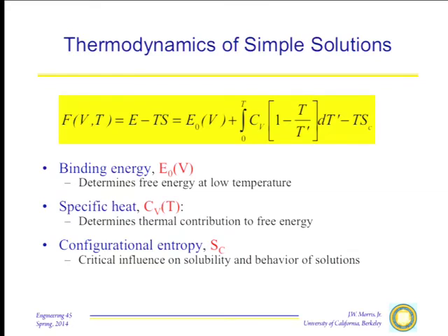It has, for example, as I'll show you in just a few minutes, the consequence that there is absolutely no such thing in the whole wide world as insolubility. You may have been taught in your chemistry course at one point or another that this oil is insoluble in water. Not true. Everything is at least a little bit soluble in everything else. And the reason is because of this configurational entropy, which always drives two components to mix together and form a solution. So let's see why that's true.